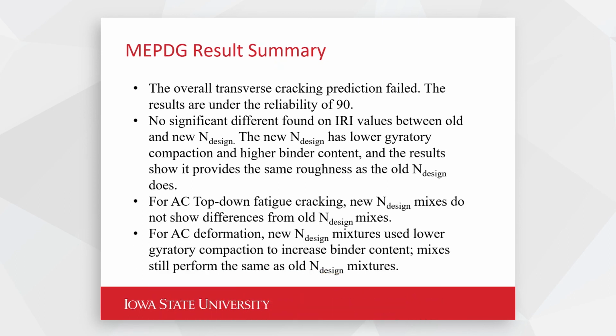The overall transverse cracking prediction in pavement ME was not being met, which would tell us that we need to have better binder criteria. And so we hope that with the improved binder criteria, that criteria would be met. But we didn't have the right mixes because they're much older under the older specification to evaluate that. But overall, the ride quality between the old and the new was statistically the same. Okay. And we didn't see any differences for fatigue cracking in the simulations for pavement ME. And we didn't compromise rutting. The rutting was essentially the same and was meeting our performance expectations.